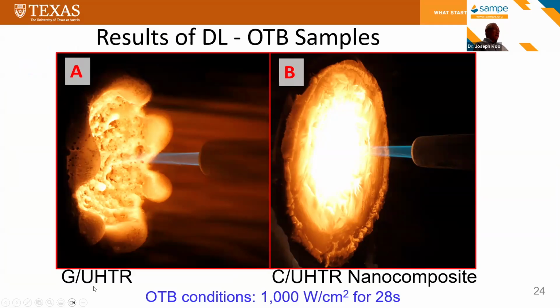This is a glass polysiloxane material exposed to 1,000 watts per cm squared for 28 seconds. The big difference: with glass, you can see all the glass melting. And here is carbon. This is a formulation that we developed, a carbon nanocomposite. We include some nanomaterials in the UHTR. These are the things that we collect during testing, and we don't just blast the material.